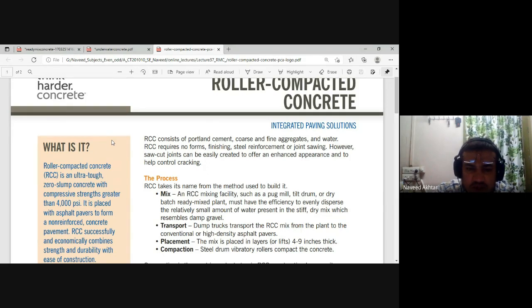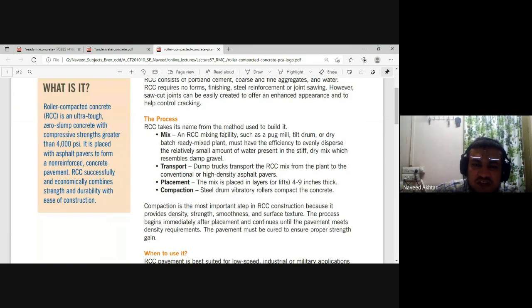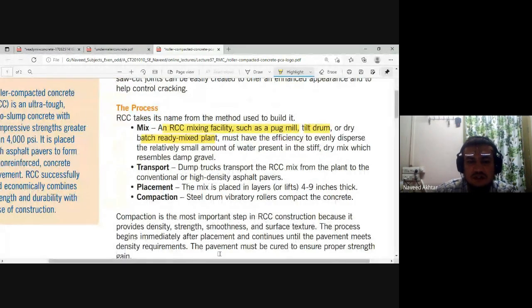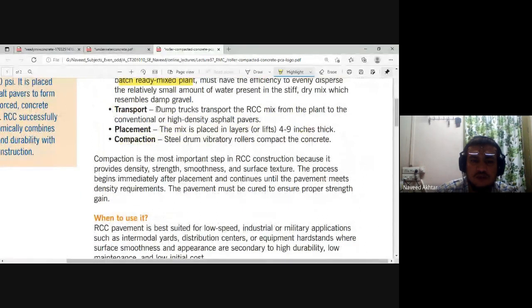So roller compacted concrete takes its name from the method used to build it. The RCC mixing facility, such as the pug mill, tilt drum, or dry batch ready mix plants, must have the efficiency to evenly disperse the relatively small amount of water present in the stiff and dry mix. So that is the dry mixing, or very stiff mix, for roller compacted concrete, and that should be managed. Transportation is through dump trucks, and at the site from the plant to the conventional high density asphalt pavers, etc. We are using them for road construction, and then for placement, the mix is placed in layers 4 to 9 inches thick, and then for compaction, steel drum vibratory rollers compact the concrete.